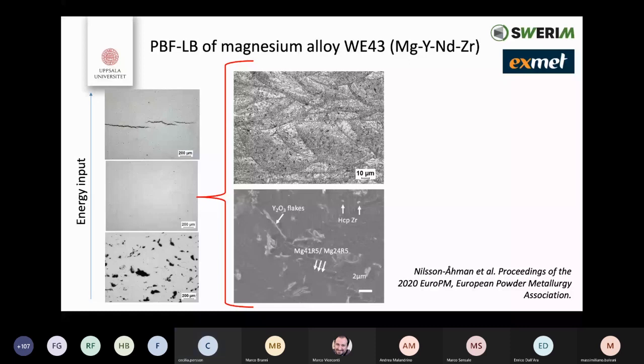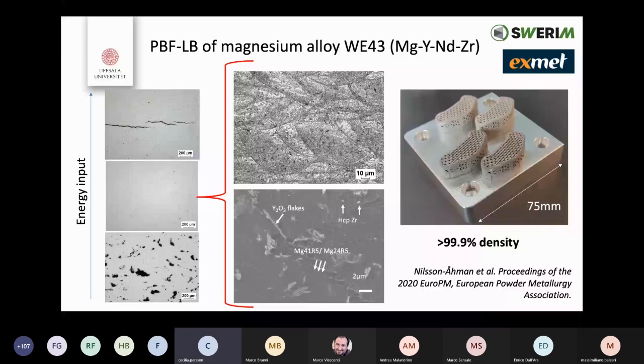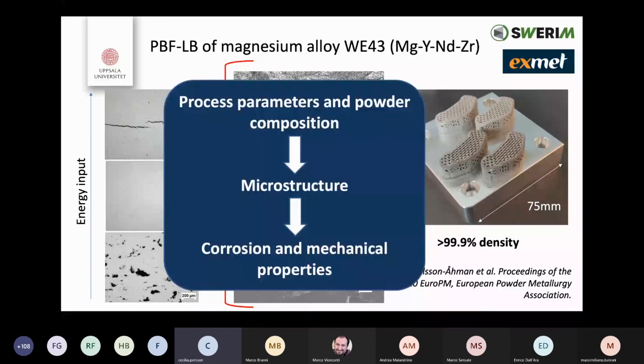But what we've at least so far shown is that it's possible to print relatively complex implants. So these are just example spinal fusion spacers, and also the bulk material is higher than 99.9% density. And what we're going into now is, of course, looking more into detail of the process parameters and the powder composition. Can we make this better? How does this affect the microstructure and thereby the corrosion and mechanical properties of the material?